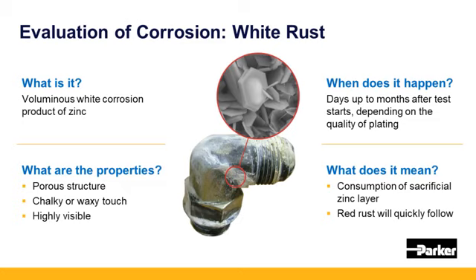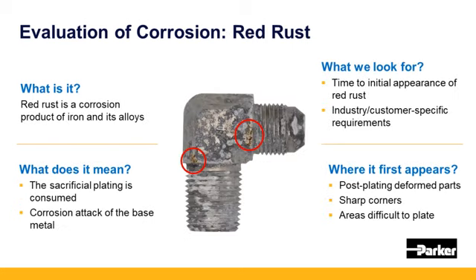The white rust can form anywhere between days and months after the test starts. Of course, that depends on how severe the corrosion test you choose is and the quality of the plating. But once the white rust appears, that means the sacrificial protection layer is being consumed. And typically, red rust will quickly follow.